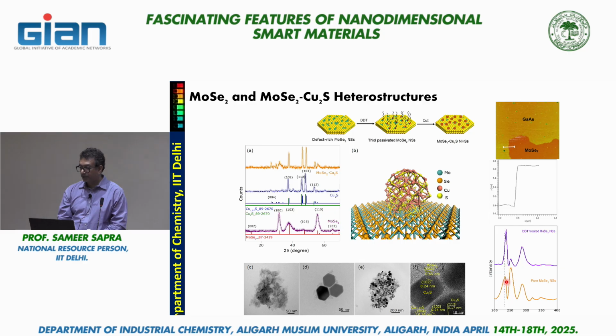If you look at the Raman spectrum over here, this is the A1G band, this is the E2G band. Sorry for not labeling them. They are present in all these 2D transition metal dichalcogenides. But this fellow in between is because of the defects. And it's present only when you do a colloidal based synthesis. Okay, and it's been reported, it's been characterized.